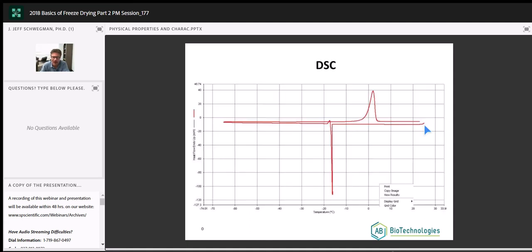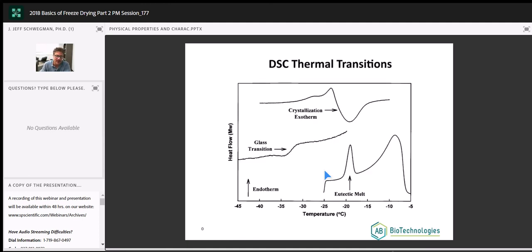is with a graph. Bottom curve is the cooling curve. We're cooling, boom, crystallization. That's the ice crystals forming. Go down to, in this case, they went down to -65. Top curve is warming, boom, there's that system melting. Notice the difference in temperature. Now, I look at this cooling curve because if it's not freezing till somewhere down here, we've got a problem. So I look at it to make sure we're freezing somewhere about negative 10, negative 20, that's fine, and then I cut it off and only look at the warming curve. The warming curve is going to give us a lot of information. Not only what are we dealing with, crystalline, amorphous, but also the critical temperatures that are associated with it.